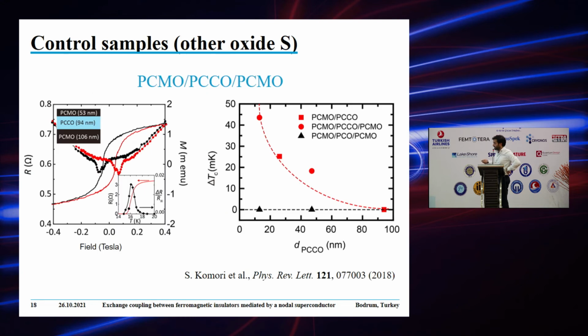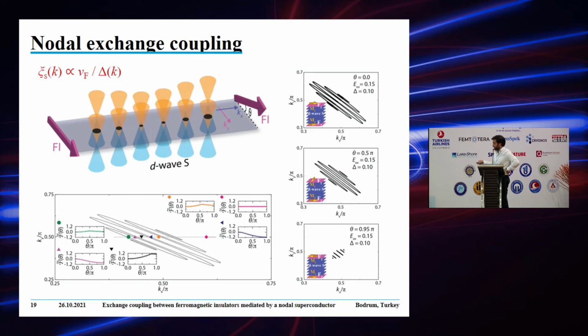We also did some other experiments. This was a parallel paper that was done by Komori, my colleague, where we put PCCO. In this case, the only thing we observed, also in bilayers, not in trilayers, was an antiparallel state favored, and this was due to the fact that there was some interaction of domain walls in these ferromagnets with PCCO. We chose PCCO because PCCO is an isotropically gapped superconductor. It's a dirty s-wave superconductor. So we were not expecting the physics that we observed there because there are no nodal quasiparticle excitations.